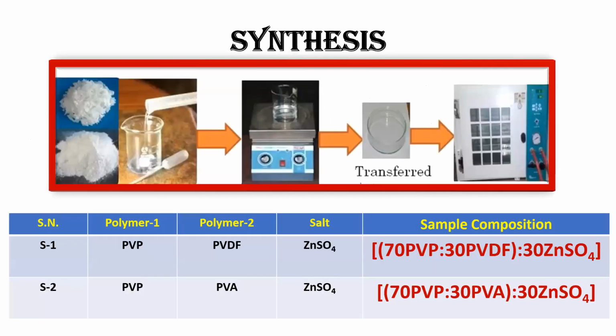The synthesis process is the solution casting process. Here I have analyzed two samples. One sample is called S1. Here 70% of PVP is mixed with 30% of PVDF, and 30% of the entire weight percentage is zinc sulfate. In sample 2, I just replaced PVDF by PVA with the same ratio, and the ratio of PVP and zinc sulfate remained constant. The solvent commonly used was DMF, because all these materials are soluble in DMF. So the solution casting method is used here.